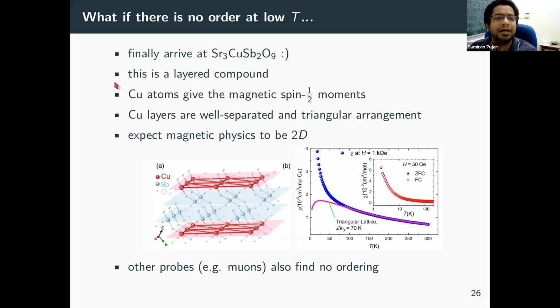So therefore, these frustrated magnetic compounds with a triangular lattice, so if you see in the structure figure, the red layers have these triangular lattice structures. So this is a way of geometrically frustrating, we say, the magnetic interactions. So there are some chemical details: the magnetic spin half moments. This is an insulating material, so the spin degree of freedom comes from these copper atoms, which give some spin half moments. And to derive this, you need to know some actual chemistry.